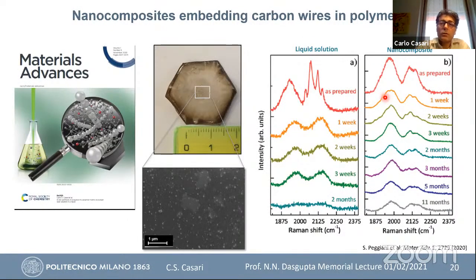So to work on the stability, we try to develop a way to stabilize the systems, and one possibility is to embed the chains or the wires into a polymer. So we produce this nanocomposite in which the systems I showed you before have been embedded in polyvinyl alcohol polymer, and we got the cover page of Material Advances for this. You can see that the stability with respect to the system in solution is very much improved. Up to almost 1 year, we can still see the signal coming from the carbon wires in the polymer.